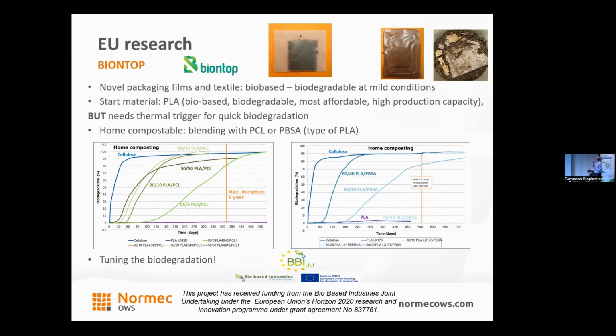But we still achieved home compostable products by blending with PCL or PBSA. It's of course depending on the type of PLA, but you can really see that the higher the amount of PCL, the quicker the degradation starts. So we could also play with the biodegradation rate. We could tune the biodegradation, which might be interesting for soil applications in agriculture, so that there is a long duration without any degradation, and then afterwards it starts degrading. Even with the addition of only 5% PCL, we could obtain a material that was completely home compostable.